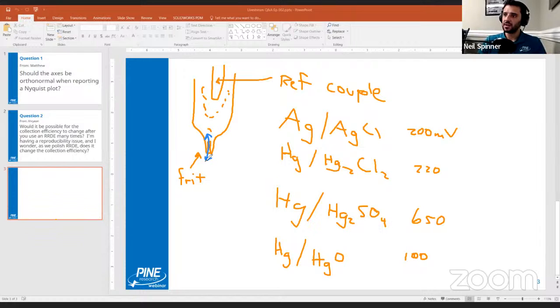Now, the ways that this can mess with things badly, the first is that if the frit is blocked or it's bad or the pores are too small or something like this, if this is really, really slow, this will give you a very high impedance. And that can make the experiment behave very poorly. It makes it hard on the potentiostat. It can mess up your data, especially if you're doing something fast like impedance. It'll only work for very slow experiments in some cases, or it still will behave poorly.